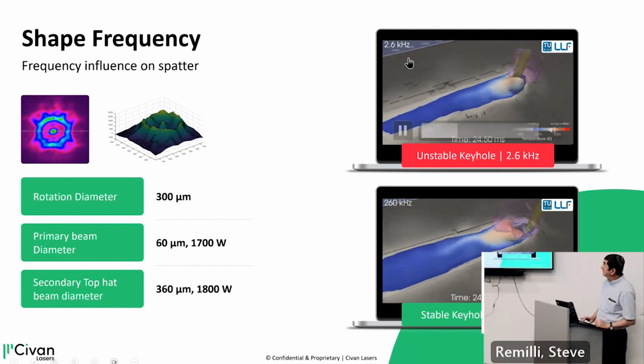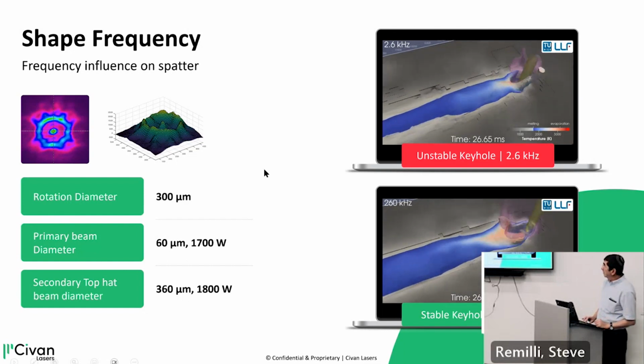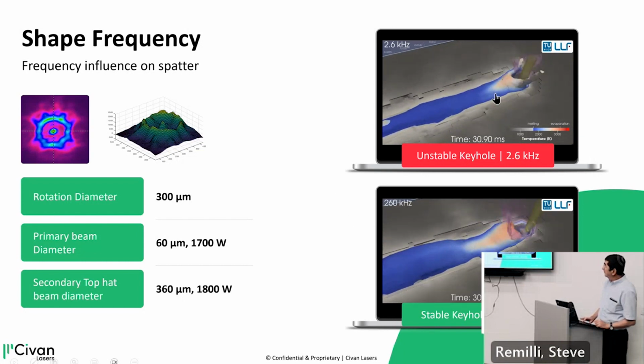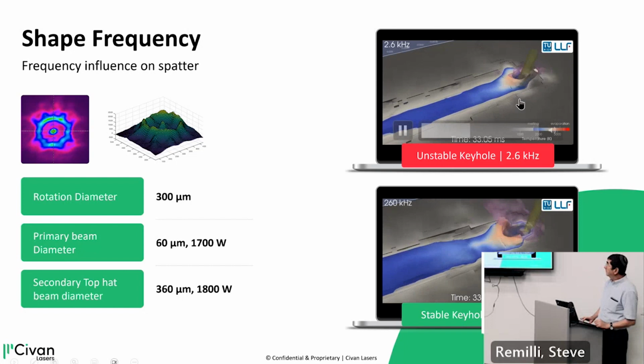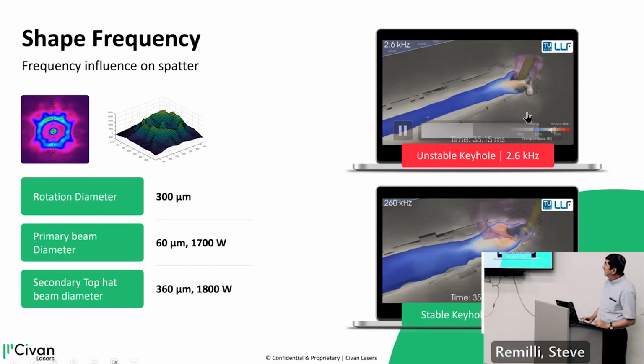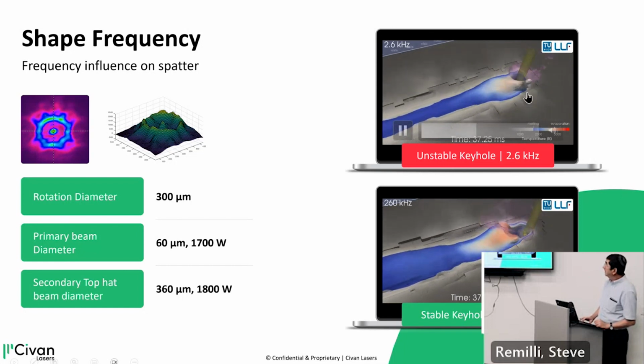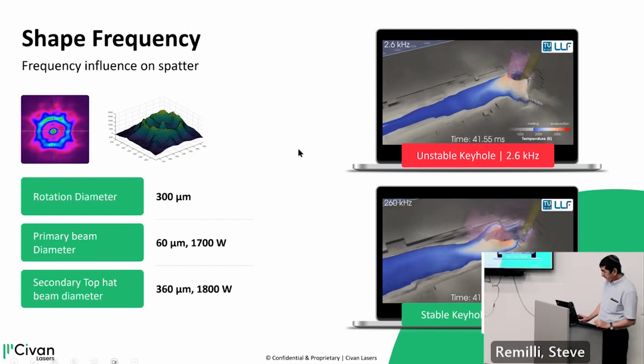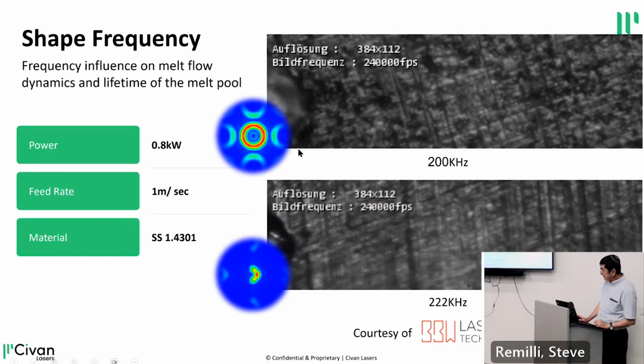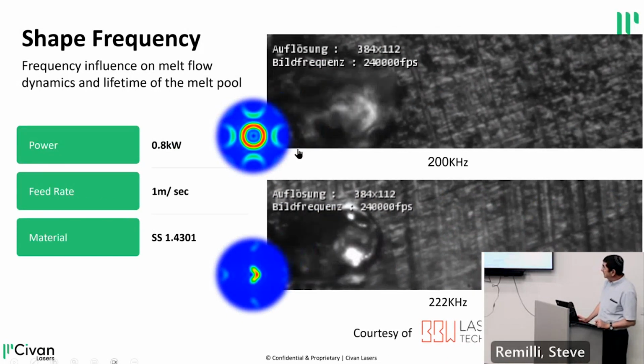And you can see that if you move it at 2.6 kilohertz or at 260 kilohertz, you get a completely different behavior, both of the keyhole, the stability of the keyhole, the spatter formation, and the length of the melt pool. And here's a real example with a fast camera.